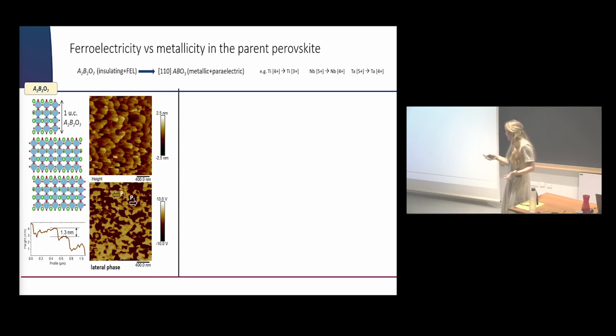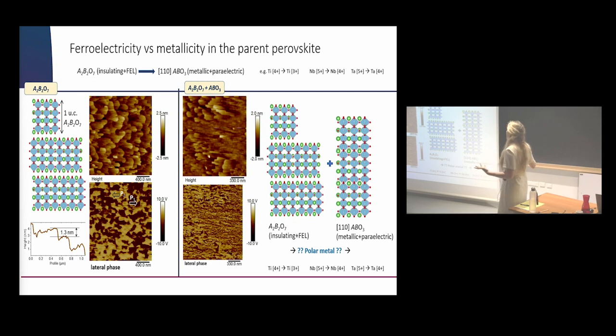But now I have some other films to show where now there's some coexistence. So you can see already in topography, you will have some flat areas surrounding these big steps. And if you look at the piezo response force microscopy, you will also see, okay, there are domains exactly where the ferroelectric is, but outside the ferroelectric, we see this noise and some type of conduction. So it looks like it can happen that we can have this insulating and ferroelectric and metallic and ferroelectric coexisting. But of course, then I think the idea is to control the switching between these two in a more controlled manner, and that's what I'm working on currently.